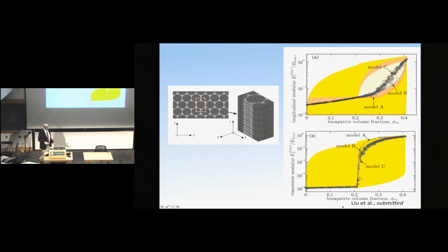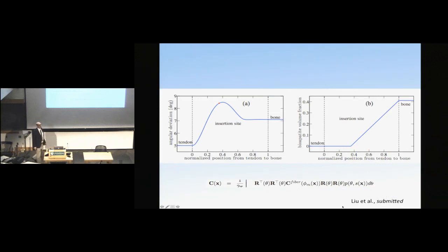And as we'll see in a second, this might have implications on how the tendon to bone attachment site might be transferring stresses to minimize stresses at the interface. So anyway, there's one more homogenization that we have to go through, which is to combine all of these data with both the distribution of bioapatite from tendon to bone, this linear rise, and then also the organization, which gives us an angular deviation S that shows up in a probability distribution function.